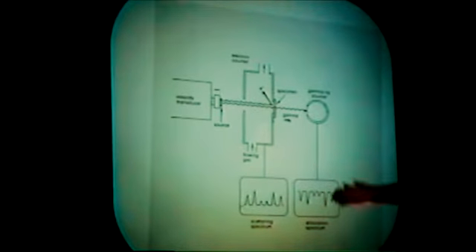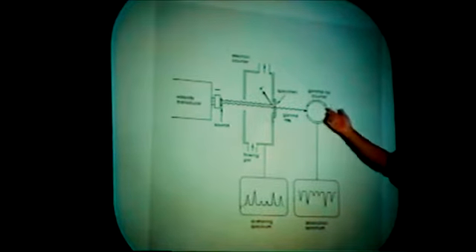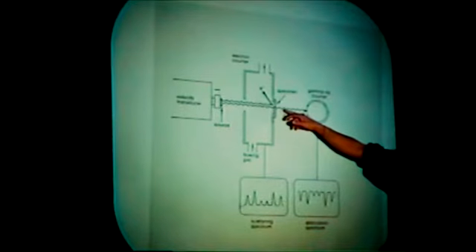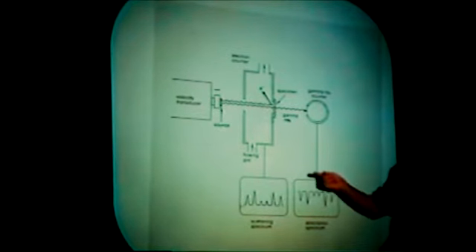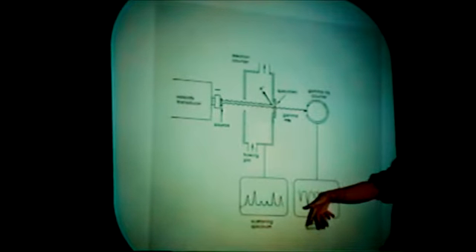Now, if the specimen is of the right thickness, this is the best way, we call it the geometric mode, you put the counter there. And whenever you have resonant absorption, and you're counting gamma photons, then the number of counts goes down at resonance. And so you have the peaks pointing down. And these are the basic components of the Mossbauer spectrometer.